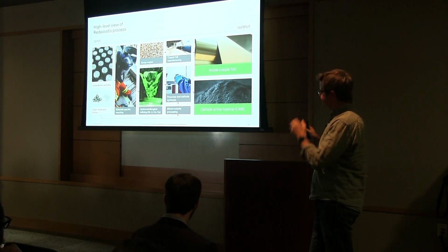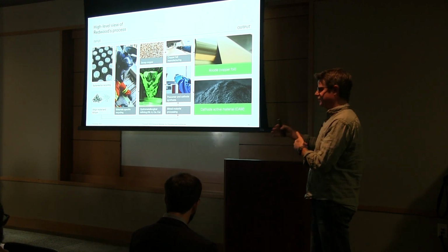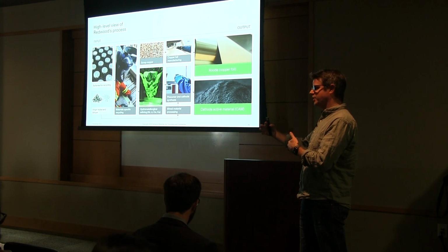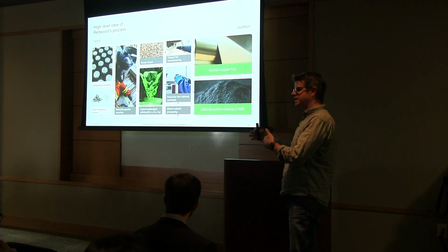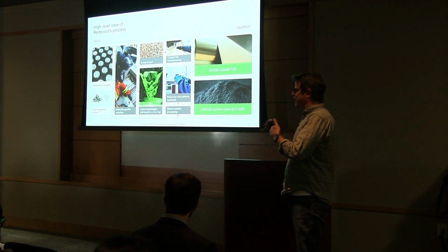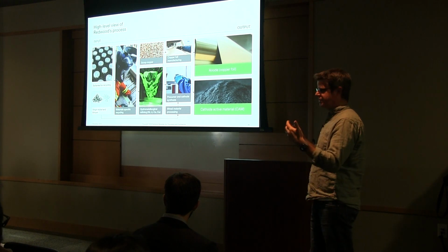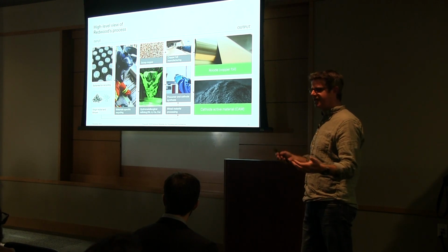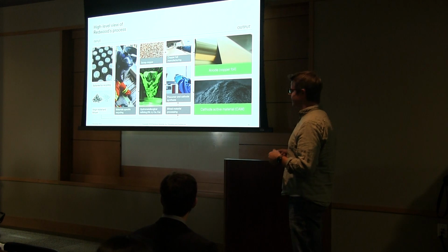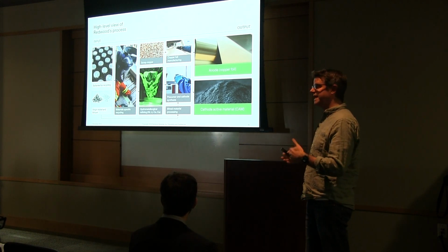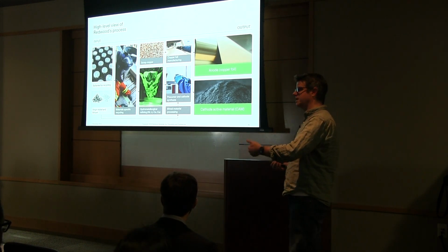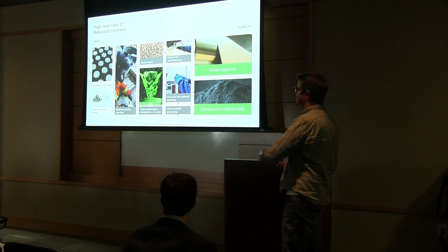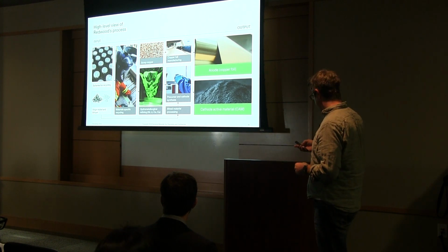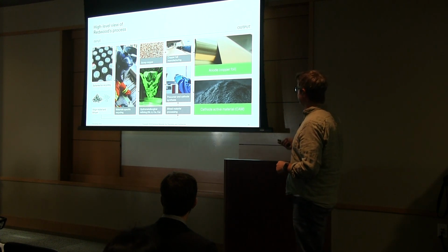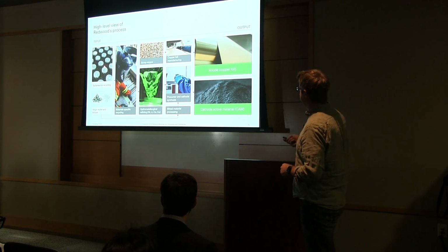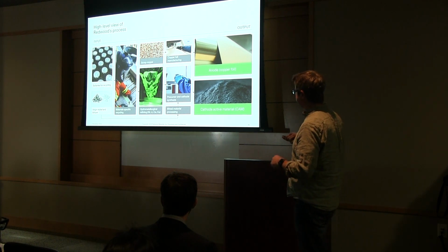So there are the first two feeds that I spoke about: the scrap from gigafactories is predictable, high grade, whereas the third type, which is really a challenge of avoiding this stuff ending up in landfills, is a lot more difficult to process. But again, this would go through a thermal processing step, followed by mechanical processing, followed by hydrometallurgical processing. Right, so that covers off that couple of boxes there.